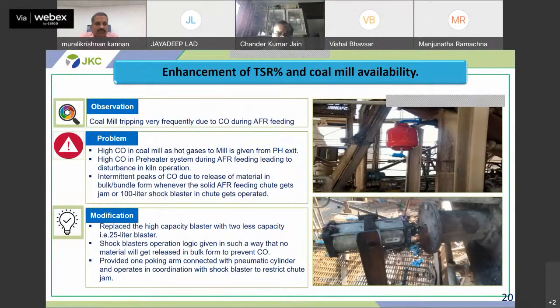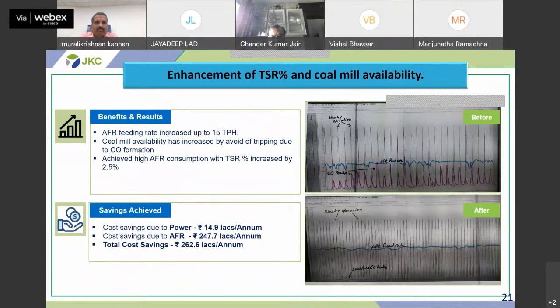So several modifications were carried out, and we have replaced the high capacity air blasters with 2 less capacity air blasters, that is 25 liters. Blaster operation logic was given in such a way that no material can release in bulk form, to prevent CO. Provided one poking arm connected with pneumatic cylinder, and it operates in coordination with air blasters to restrict chute jamming. By these modifications, we were able to increase our AFR feed up to 15 TPH, avoided coal mill tripping due to CO formation, and increased our TSR by 2.5%.